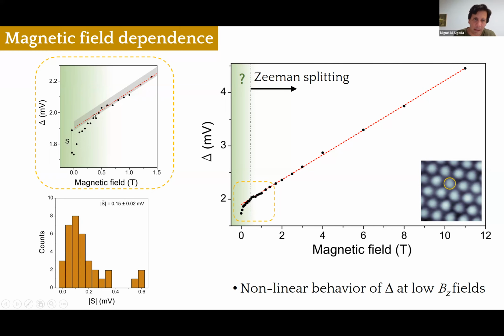So this gray band that you see here is the error band that we calculate in the whole regime. So this displacement is totally real, and it ends up like 200 microelectron volts below where it should be. However, this distance is pretty small. It's typically 100 or 200 millivolts.